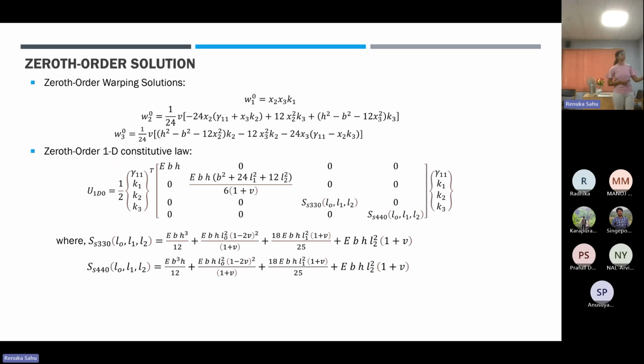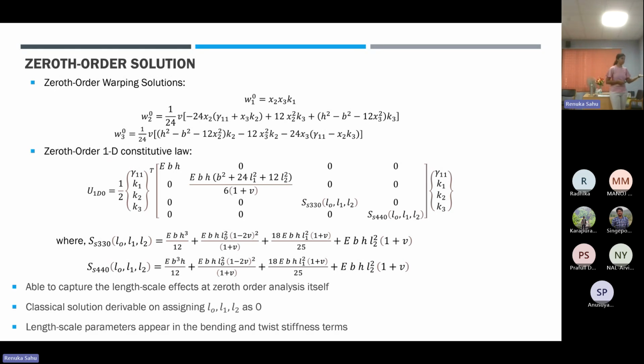As you can see, the material length scale parameters L1, L2, and L0 now appear in the zeroth order 1D constitutive law, which was not present in the classical model. So we are able to capture length scale effects at the zeroth order analysis itself. If we assign L0, L1, L2 as zero, we get back the classical results, which proves the model is working fine.